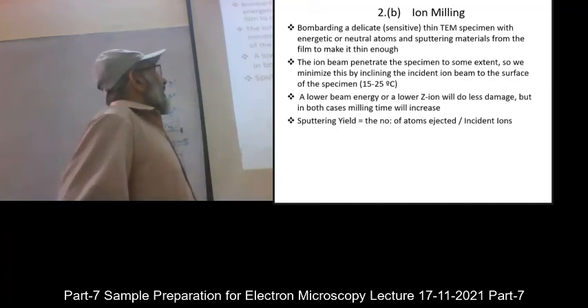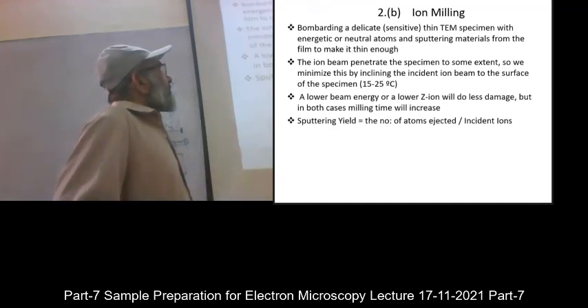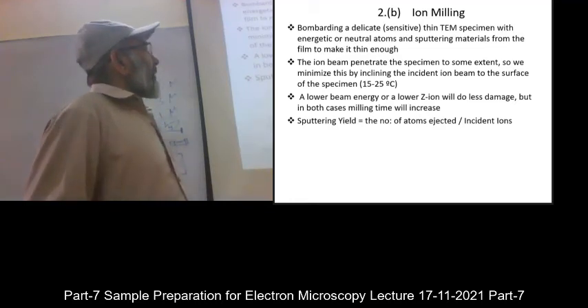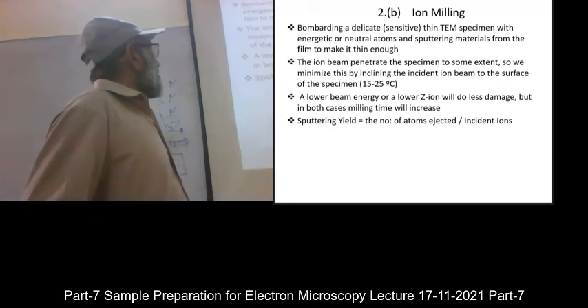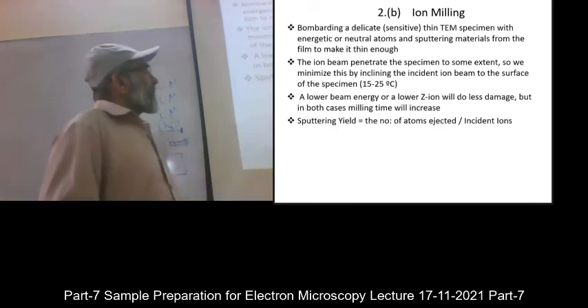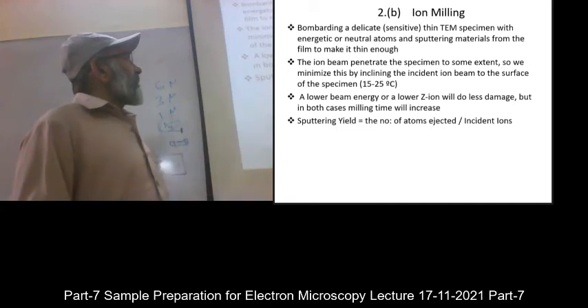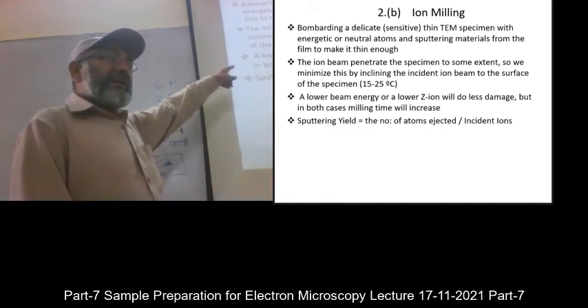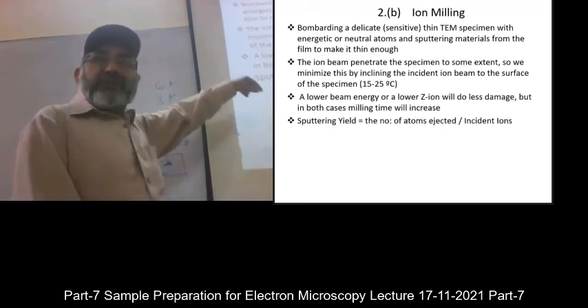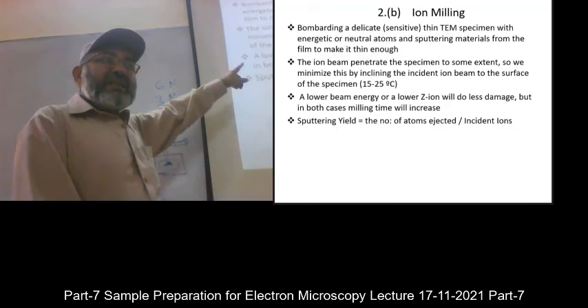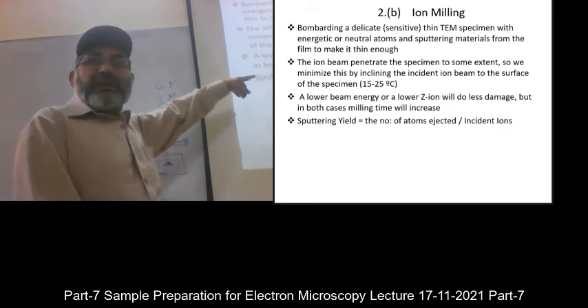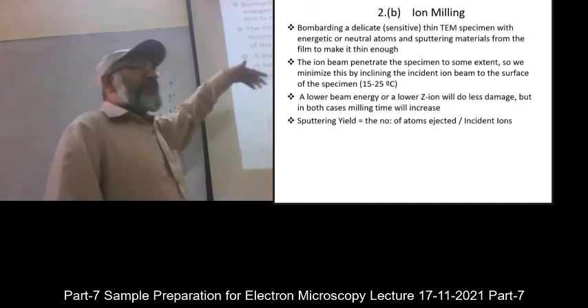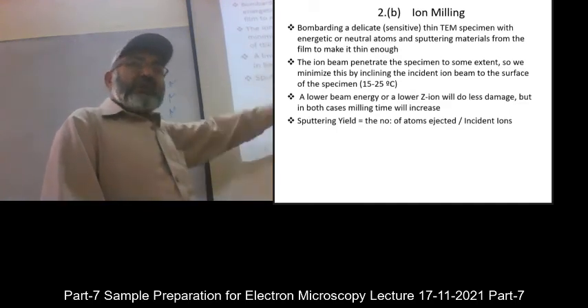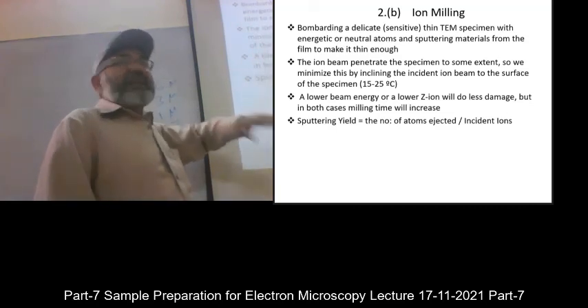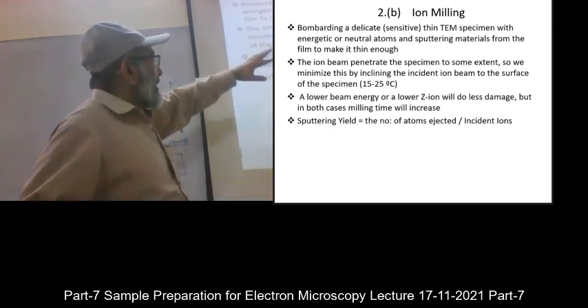Ion milling, as I have explained to you several times, is bombarding a delicate specimen with energetic ions or neutral atoms and sputtering materials from the film to make it thin enough. The ion beam penetrates the specimen to some extent, so we minimize this by the incident angle, right? So when the incident angle is higher, it will do deep grinding, and when the incident angle is shallow, it will just skip the surface and it will not go deep down, and you will have more thin area if the sample is near that critical state.